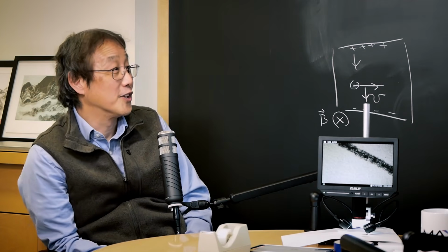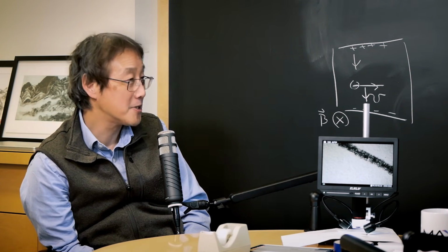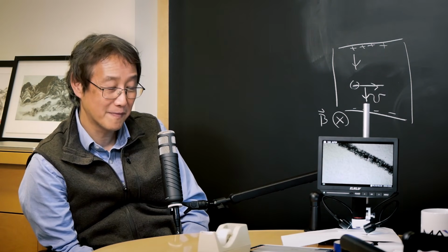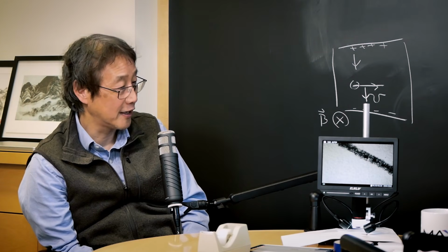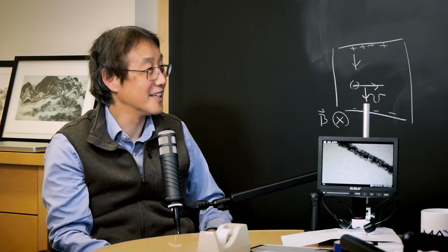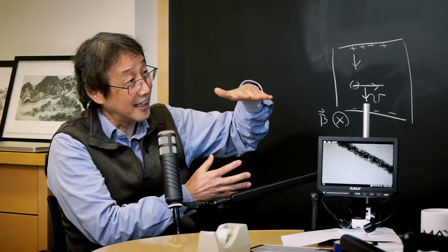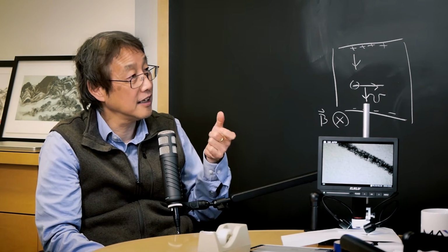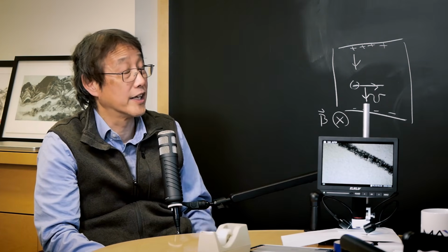Right. So the task we had was making the AFM tip made of graphite blocks. Among my first generation students, Yambo Zhang, who is now a professor at Fudan University, is a very creative guy, and he was very motivated by the potential project I described. So he started working on that idea, and after about a year and a half of hard work, he started to produce this nano pencil, basically an AFM tip made of graphite block, and then with a little bit of effort, he started to cleave rather thin crystals onto a silicon oxide substrate, a silicon wafer.